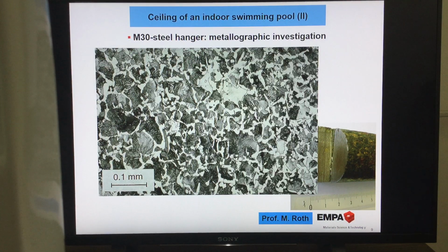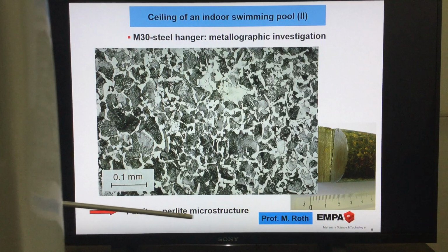And you know the phase diagram of iron carbon, and when you think of the eutectoid, where is the eutectoid? The carbon where you have 100% perlite, it's at 0.8% carbon. So when we judge this, the amount of ferrite, I guess there is about in the range of 0.6 to 0.7% carbon inside. Okay, ferrite, perlite, microstructure.